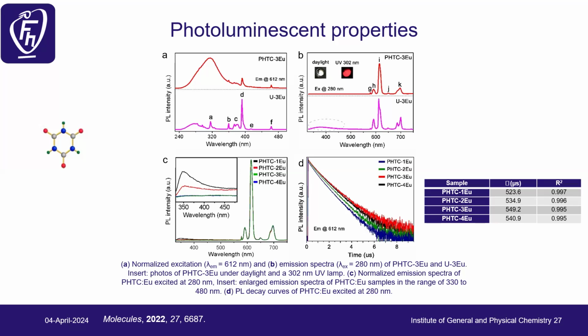And here we can see the emission absorption lines, europium in this case. And this 393 is the most intensive one. At the end, on the right, on the B, we can see that we have emissions just of the europium. And in this case here, we have a slight phosphorescence of the linker, because what can happen is that we can transfer back a small amount of energy from the europium or lanthanide to the linker.